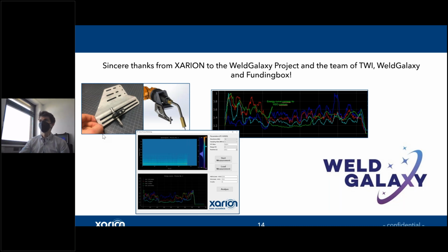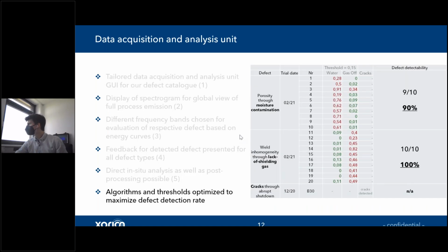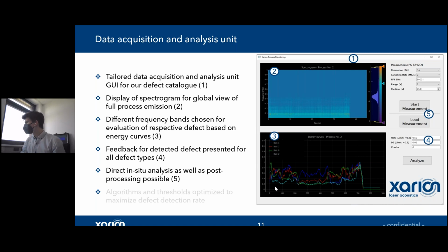That's a really good question, and thanks for letting me address that. Let me pull up the slide again. Okay, so you see on our GUI the various energy curves, and they correspond to different frequency bands. In general, the emission is very broadband, and there's a lot of high ultrasound content. And one of the nice physical properties about high ultrasound is that it does not propagate as far as low frequency sound. In the audible range, you easily propagate the sound waves many, many meters. But in ultrasound, it's more on the centimeter scale. So when you focus on the high ultrasound frequency bands, you are quite robust against these neighboring MAG processes.